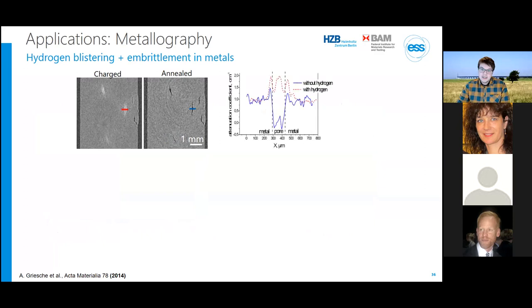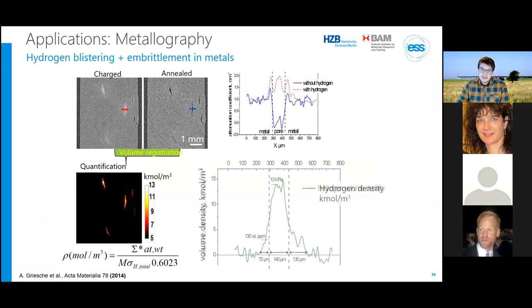And between that, then you have, of course, a different attenuation. And this can then be used to even quantify the amount of hydrogen and the pressure inside the bubbles from this data. I should add, however, here that the amount of hydrogen in this example was very large. And because embrittlement can be caused by just very tiny amounts of hydrogen, we as a community are actually working very hard towards increasing the sensitivity of the methods towards much smaller amounts of hydrogen.